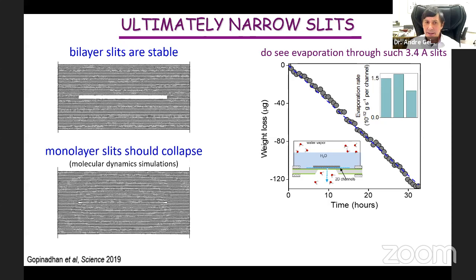even when we make capillaries with a single atomic plane extracted, they allow water through. And this is not an artifact. This is the same data in this case for three different channels. We do see extremely small, but reliably see, water flow through those.